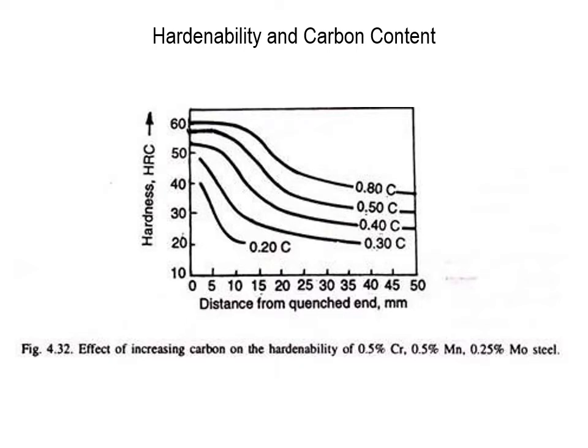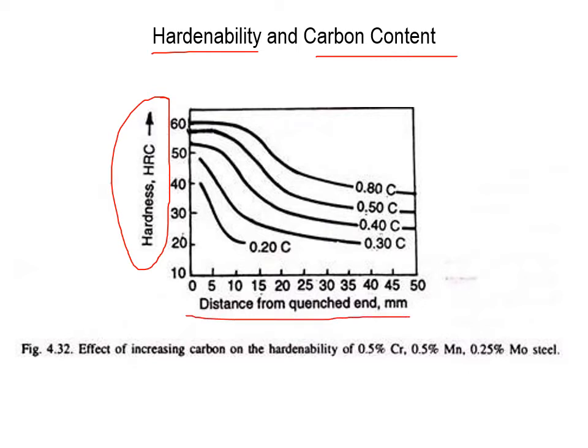In this chart here, we take a look at the relationship between hardenability and the carbon content. So we can see over here we have our hardness again still on our y-axis, and our distance down here on our x-axis from the quenched end, given this time in millimeters. And what we have in the figure itself is the effect of increasing the carbon on the hardenability. So you can see we have 0.3, 0.4, 0.5, 0.8, and down at the very bottom here are 0.2.